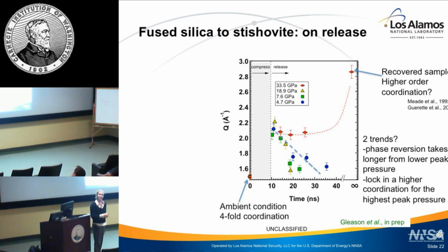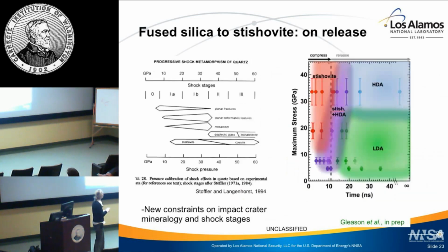Moreover, we could think about our data in a different way and talk about, instead of an equilibrium phase diagram that we think of commonly from the static compression diamond anvil cell community, a non-equilibrium phase diagram. In other words, now we have pressure, temperature, and time. So here I show our maximum pressure achieved and time, and I've sort of clustered out the different phase stability regions that I access, but now as a function of time.